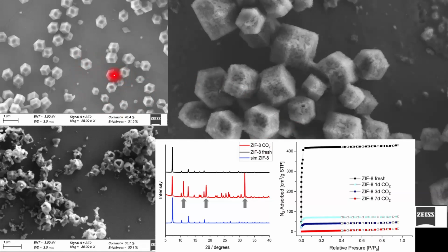Here you see original ZIF-8. These are relatively large nanoparticles because I wanted to see the holes. And if you put them in contact with a lot of CO2, you end up with these capsules. It's completely destroyed. If you leave it inside the incubator, from this, you go to this. Can you see the holes? And what happens is that we have a new zinc-based structure. I have found a similar diffractogram, but we are still working on that.